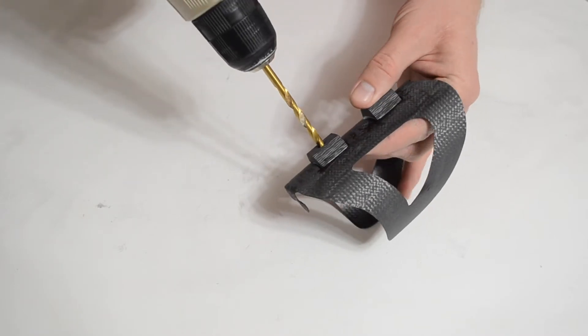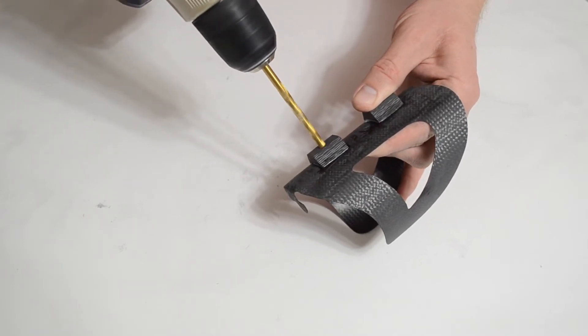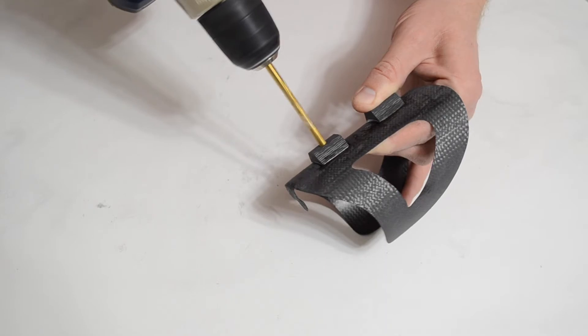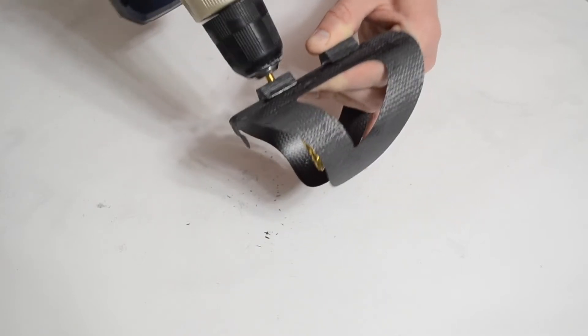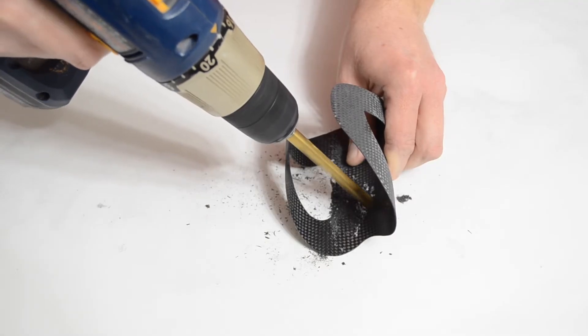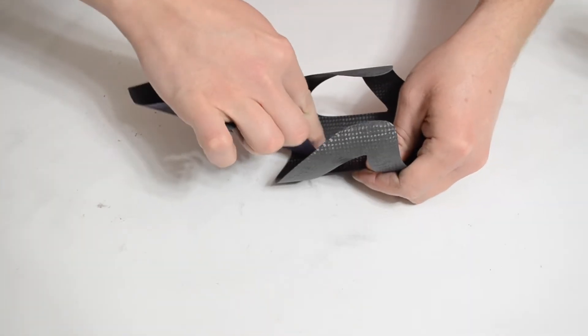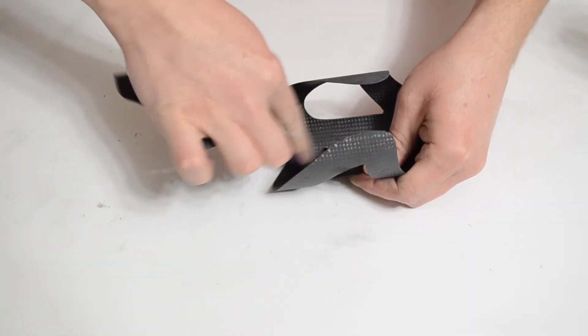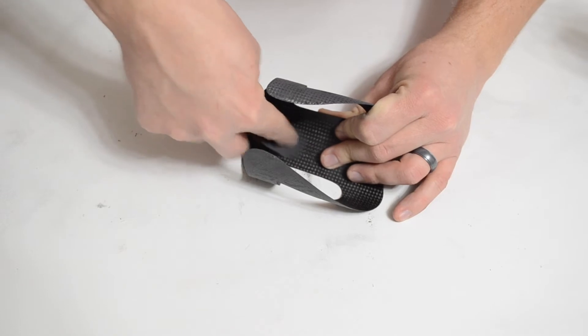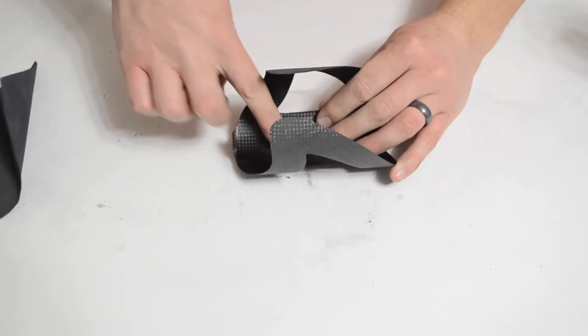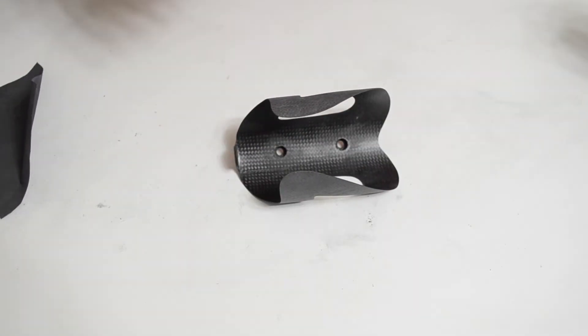I used the existing holes in the blocks to drill out the final hole. And then I used the 3/8 bit from the other side to go just past the first few plies to open up the hole. You don't want to go all the way through, or else the screw will just slide all the way through the hole. A little sandpaper to clean up any fiber break out, and we're ready to test fit our screws.